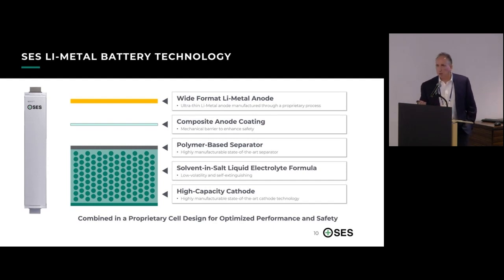We're using a polymer-based separator, which is a very common separator, similar to what you'd find in a lithium-ion battery today. And we're applying a solvent-in-salt, proprietary liquid electrolyte, which is non-flammable and very stable on lithium. And then we're using high-capacity cathodes.